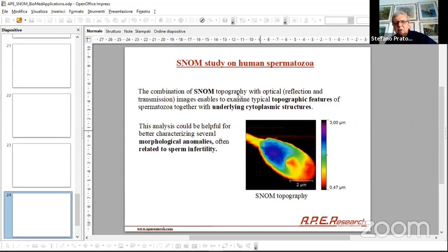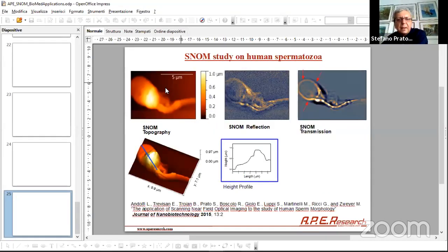We did the same, for example, with some human spermatozoa. Here you see the topography, and we recently also published some new papers. This is a 3D image obtained with FM. It's quite nice, but we want to study the tail of this spermatozoon and to see the inner part. With FM, you can watch the tail, but in this case, with the SNOM, we were able to put in evidence some structures like this corona and these small clusters.